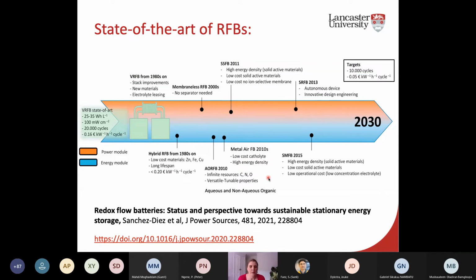So I'm not even going to begin to talk about all of these, but this is from a recent paper that came out this year, which is a nice summary of the perspectives of redox flow batteries and where they're heading for 2030. So you can see the state of the art for flow batteries. You're looking at energy densities of around 30 watt hours per litre, and the current cost about 0.16 euros per kilowatt hour per cycle, whereas the targets are a minimum of 10,000 cycles, and the target is to try and drop that price per kilowatt hour per cycle down to 0.05 euros. So there's a huge cost objective to try and really make redox flow batteries competitive, if not more competitive than lithium ion systems.